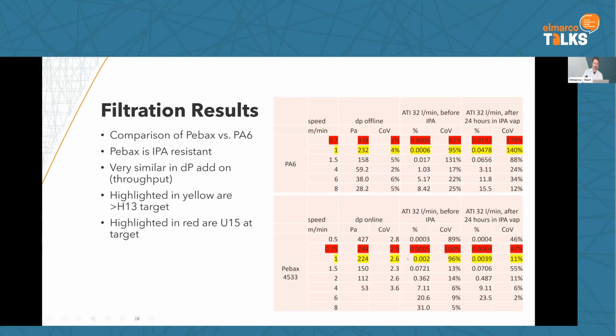The important thing is that this material is a lot more flexible and durable than PA6, which is very crystalline and can be a little bit fragile and is subject to cracking and things like that when you start to do downstream processing.